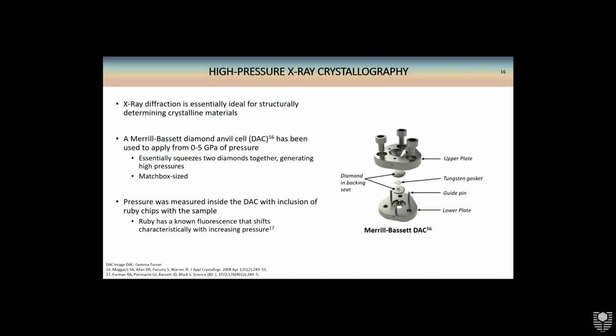These are devices that essentially squeeze two diamonds together where the tips have been cut off. It's a very small surface area, so a little bit of applied pressure between the diamonds generates very large pressures in between. The diamond anvil cell itself is actually quite small, about matchbox sized. There's a little tungsten plate that goes between the diamonds where a hole's drilled through, a few hundred microns across, and that's where the sample gets loaded. You measure pressure within one of these cells by including a few ruby chips inside with the sample, since ruby has a known fluorescence that shifts characteristically with pressure.